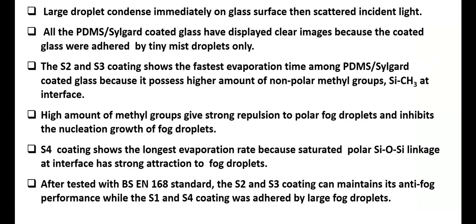The S2 and S3 coatings have the fastest evaporation time among the PDMS/Sylgard coated surfaces, and this possesses a higher amount of non-polar methyl group, SiCH3, at the interface. A high amount of methyl group gives stronger repulsion to the polar fog droplets and inhibits the nucleation and growth of fog droplets. The S4 coating shows the longest evaporation time because of the saturated SiO-Si linkage at the interface, a strong attraction to the fog droplets.